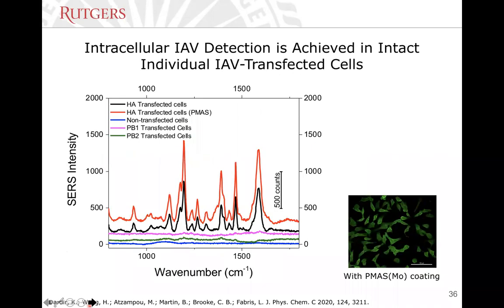The last step was to bring the particles into a cell and see if they actually recognize a virus present in the cytosol. So we took HeLa cells. HeLa cells are easier to transfect with plasmids. So we took three plasmids, one coding for hemagglutinin and two others coding for PB1 and PB2, which are two other segments in influenza A, for which our particles were not designed. And so we saw what? When exposed to either non-transfected cells or to cells that were transfected with PB1 and PB2, we see no signal. And when we expose the particles to cells that have been transfected with the hemagglutinin segment, the signal goes on.